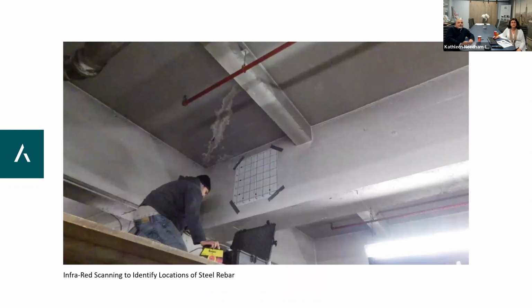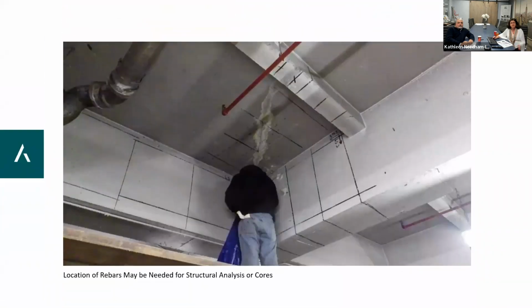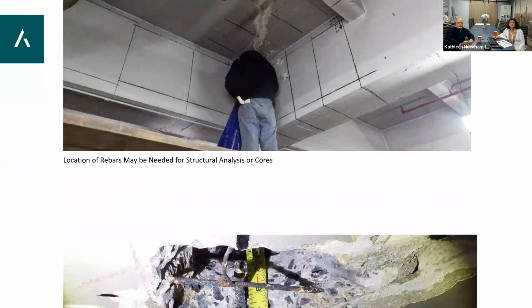In this case, this is a reinforced concrete structure. We needed to locate where the rebars were and find out what the size of the rebars were inside the concrete. So we brought in an infrared testing company to do a scan of the concrete. And as you can see, the contractor scans the concrete and maps out wherever he detects there's steel located. And if I have to do any core samples, I want to know where the steel is, because I want to make sure I can core through the concrete without interfering with any structural steel.